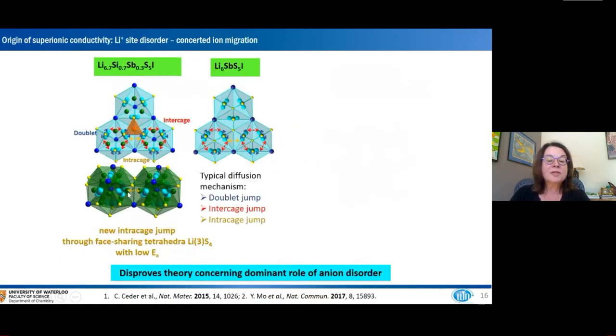So one of these sites actually sits in the intercage transport pathway, and it provides a metastable site for ion diffusion. And this is what results in the high conductivity.